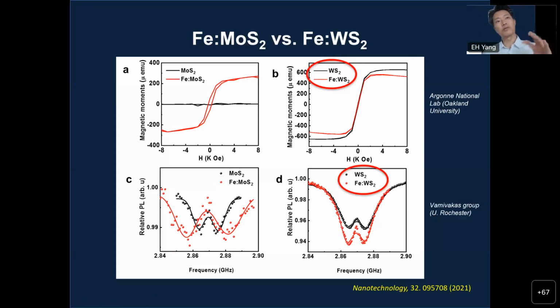That means if you see something from a global effect or from residues of iron atoms somewhere, for example, you would have to see the same thing from this iron doped tungsten sulfide. As you can see, however, at room temperature you don't see anything, whereas at room temperature the iron doped molybdenum sulfide is ferromagnetic, and iron doped tungsten sulfide is paramagnetic. There's no hysteresis, which clearly proves that iron doped molybdenum sulfide is, number one, ferromagnetic. Number two, this ferromagnetism comes from the substitutionally doped iron atoms. And another confirmation is from this nitrogen vacancy center, where iron doped tungsten sulfide does not show the increased Zeeman splitting, while iron doped molybdenum sulfide shows increased Zeeman splitting at room temperature.